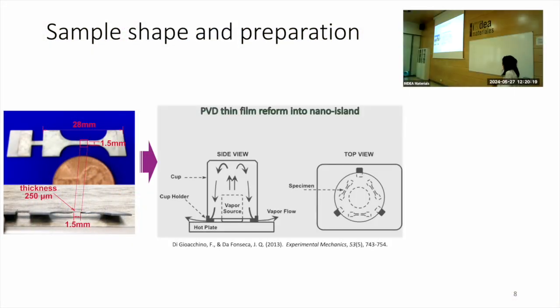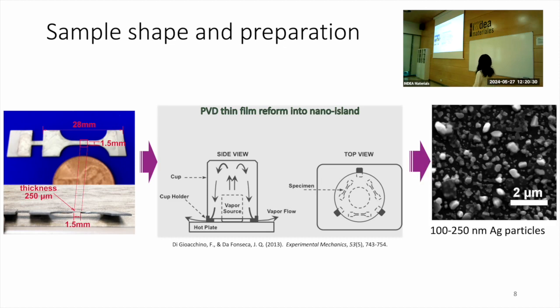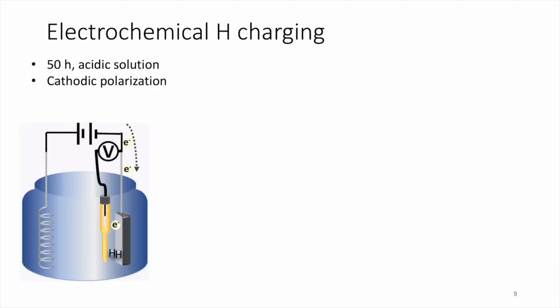And because we want to track how the slip is forming, right? Then we want to have something that we can use to track. So we introduce some pattern by doing some PVD thin film, and we reformat it into small nanoparticles. So we use those silver nanoparticles on the surface of our sample to track slips. After that, we introduce the hydrogen into the material in two ways.